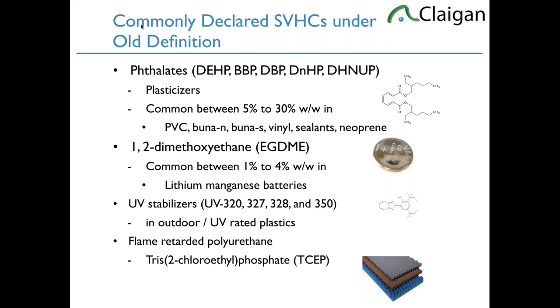The UV stabilizers, the benzotriazole families. Basically, plastics are not normally UV stable. So for example, if you have a water bottle at your desk and you look, hey, it's transparent. Light can go through it. Yes, visible light goes through it, but UV light does not. It gets blocked and absorbed. The UV spectrum gets blocked and absorbed by most plastics, then it has to dissipate the energy, and usually by chemical change or aging or discoloring. So outdoor rated or UV stabilized plastics often use a UV stabilizer, of which these four were fairly common. And since they're usually in the outer enclosures of outdoor products or UV rated products, they're pretty high concentration over